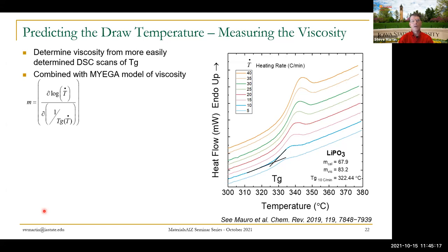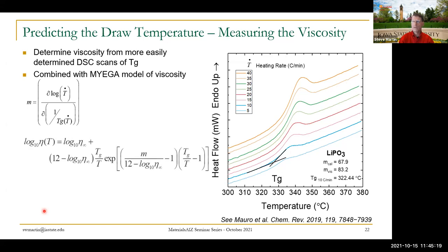That's not only very powerful at fitting data, but you can measure the parameters of the MYEGA model by doing DSC experiments. You don't have to do full viscosity measurements. There are a lot of parameters, but one of the most important is the fragility exponent, m. And we get that by doing a series of heating and cooling experiments, and so we can get the fragility parameter.